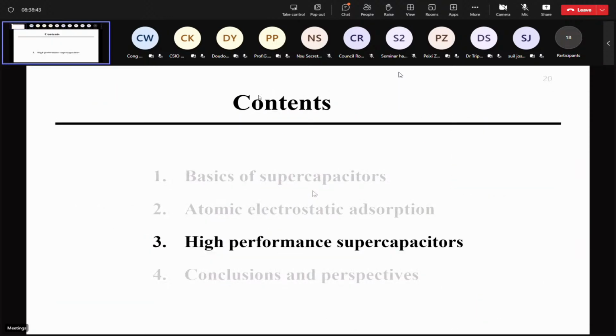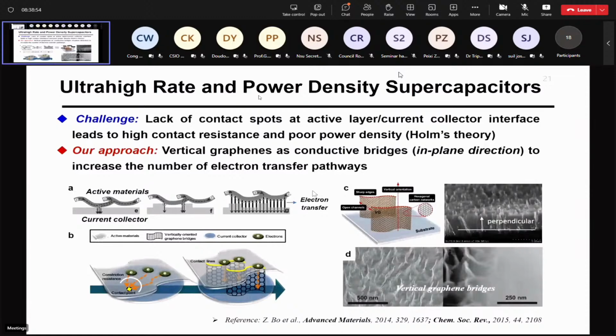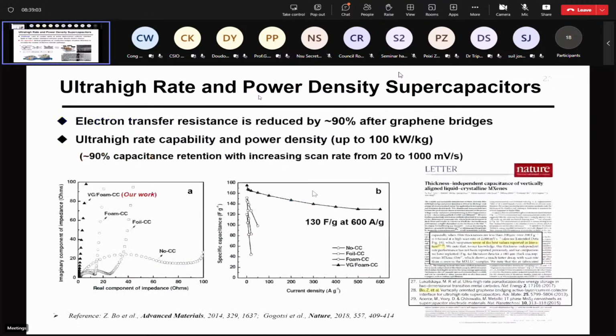Based on this work, we try to achieve some high power and high energy density supercapacitors. Here we use the vertical graphene as both the active material and the current collector. Then we can get quite a low electron transfer resistance and achieve ultra-high rate capability and power density.